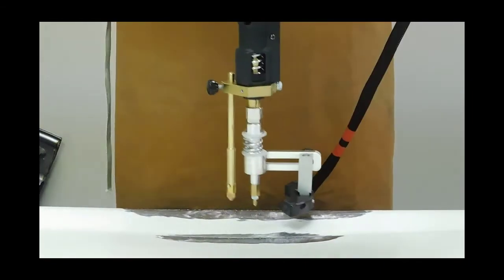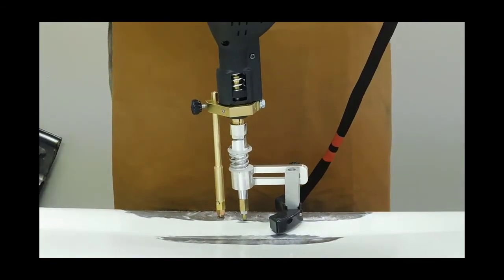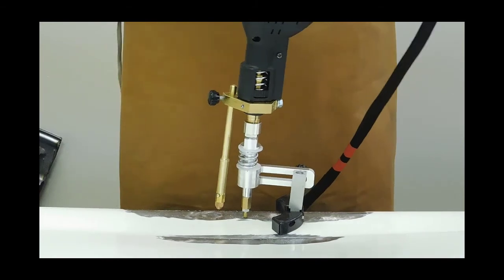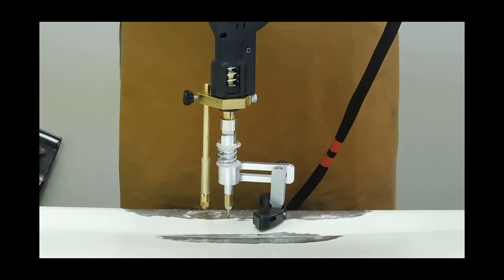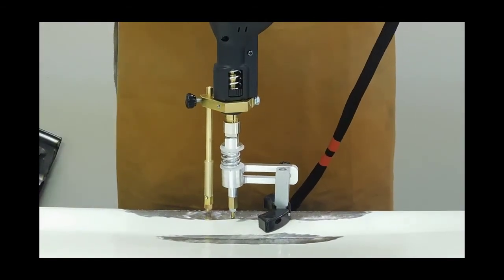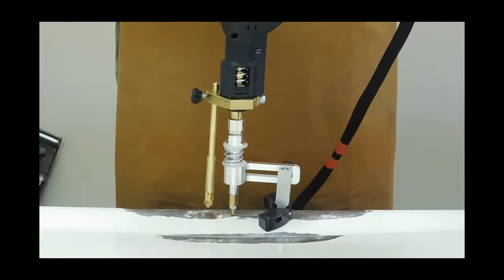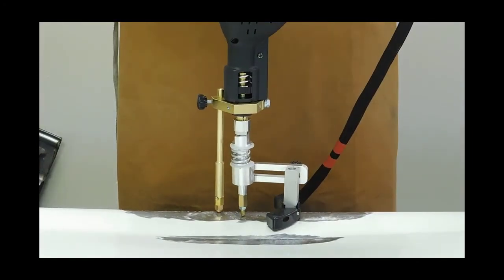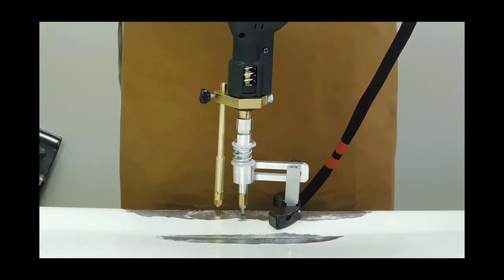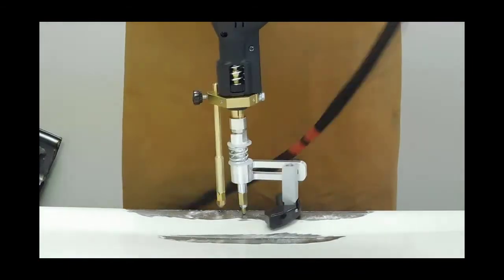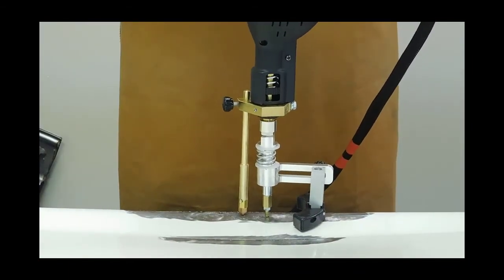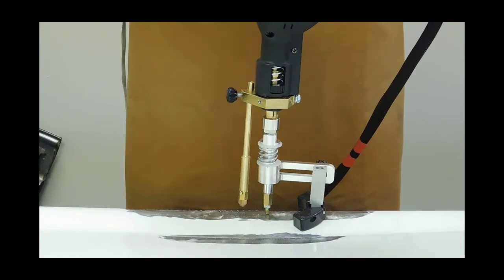Once the tip is welded, use the body of the welder to gently prod the dent out of the panel surface. When the pull is completed, rotate the welder in a clockwise direction 90 degrees to break the weld tip off the panel. Move and repeat the process as often as required to finish the repair. Please note, over-welding the dent stick and over-pulling can result in damage to the panel. Caution should be taken not to over-pull the repair.